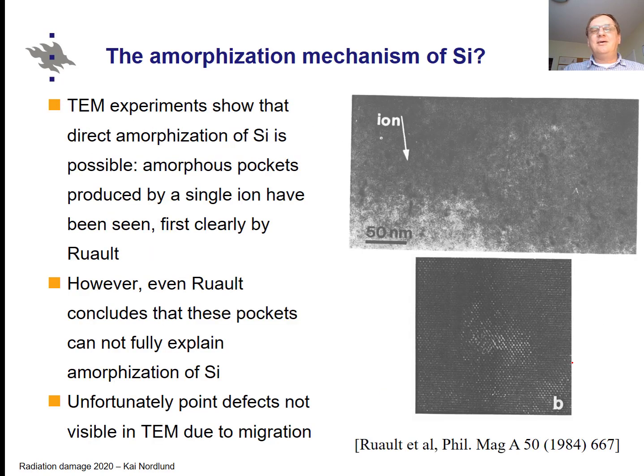Both models have correct elements. Silicon does amorphize and you do form amorphous pockets, which have been seen both in simulations and in experiments on the nanometer size scale — each dot here is an atom, so this is a few, maybe 10 nanometers. But even the people who found these pockets concluded that there are not enough pockets to explain the full amorphization of silicon.